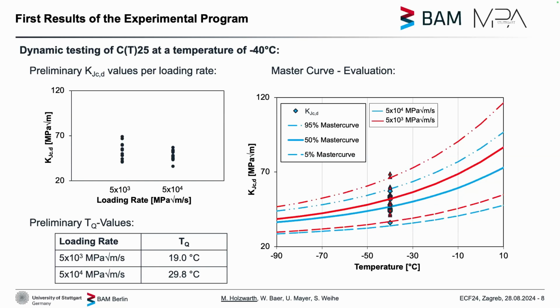And our preliminary T0 values led us to this master curve. And those tests are now for minus 40 degrees. And we see those master curves are not a perfect fit, which is to be expected because not only the temperature is playing a role in the ductile to brittle transition range, but also the loading rate. So different loading rates should lead to a little different master curve. And now we just have to test at more temperatures, and those fit beautifully into those tolerance bounds.